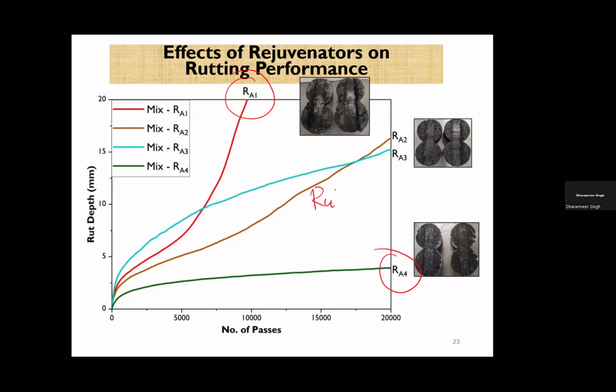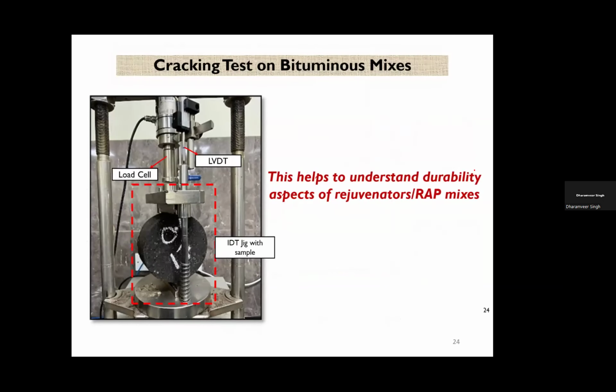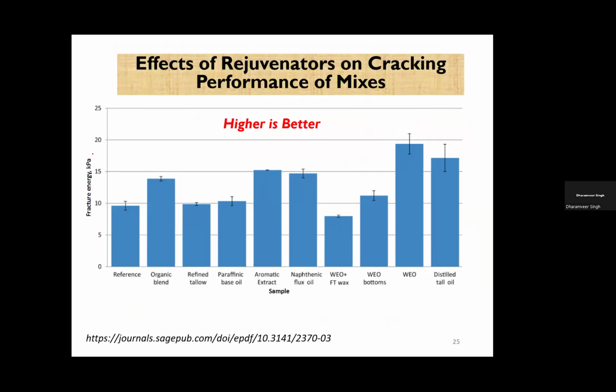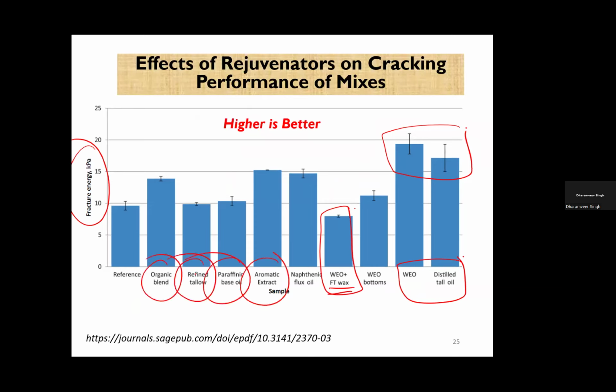One thing is rutting. The other thing that happens when you use a rejuvenator is that cracking becomes another issue. It should not happen that your mix becomes quite aged and then you see the problem. Therefore, cracking also becomes quite critical. If you see this result here, higher is better. These two rejuvenators are performing very well. But the WEO and the wax are performing not really as expected. So there are different kinds of rejuvenators. Organic blend is there, refined tallow is there, paraffin oil is there, aromatic extract is also there, and there is different chemistry that works out, and this is going to give different performance.